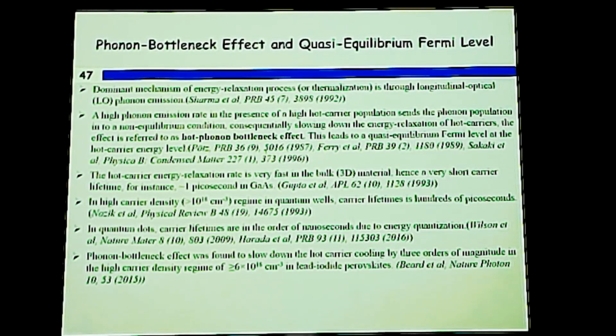So to find the connection, let's look at the physical property of the material, studied by many people over many years. When there are photoexcited carriers, they undergo an energy relaxation process, and the dominant mechanism is LO phonon emission. And when there is a high emission rate, the LO phonon population will go out of equilibrium. When that is out of equilibrium, further phonon emission is slowed down. And that is called the phonon bottleneck effect.